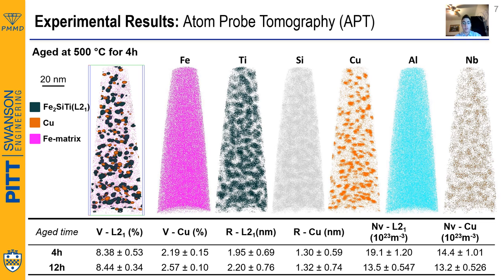This is a huge success, since it proves that this type of precipitate is the main responsible for the high hardness reported previously. Moreover, we see in the table that even after 12 hours aging, the volume fraction of the precipitates and their size have not changed much, which then explains why the hardness remains constant throughout time.